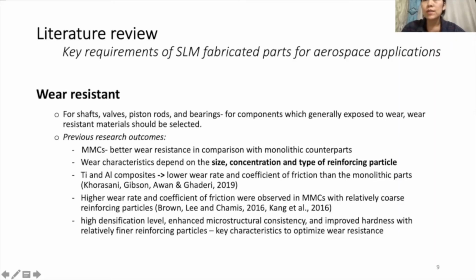According to previous studies, selective laser melting processed titanium and aluminum composites demonstrated lower wear rate and coefficient of friction than the monolithic aluminum and titanium parts. Furthermore, studies done by several researchers state that there is a remarkable dependence between wear resistance and the size of reinforcing particles. So it means that higher wear rate and coefficient of friction were observed in metal matrix composites with relatively coarse reinforcing particles due to the low densification level and the structural inhomogeneity. Also, partially melted or unmelted regions of metal powder directly influence the interfacial bonding and negatively affect the wear resistance. All in all, high densification level, enhanced microstructural consistency, and improved hardness with relatively fine reinforcing particles are a key strategy to obtain better wear resistance for metal matrix composites.